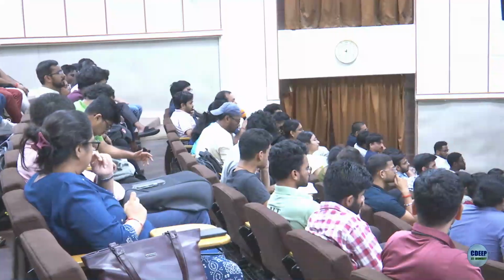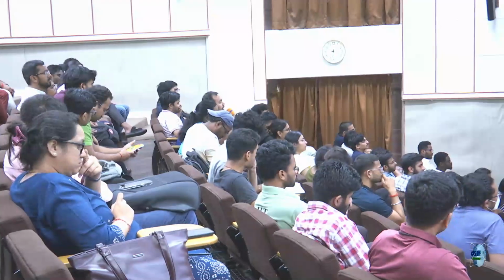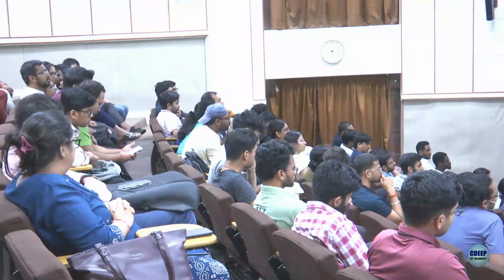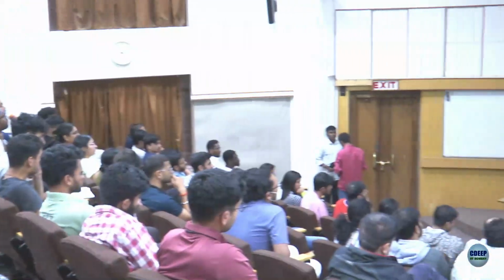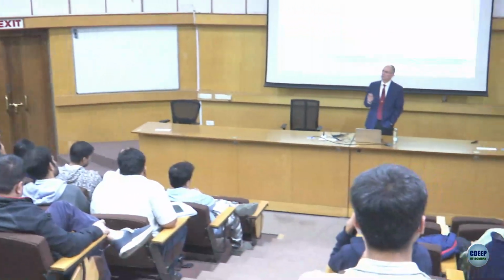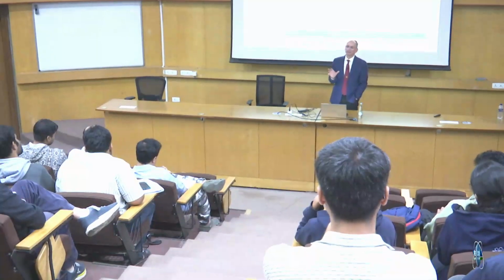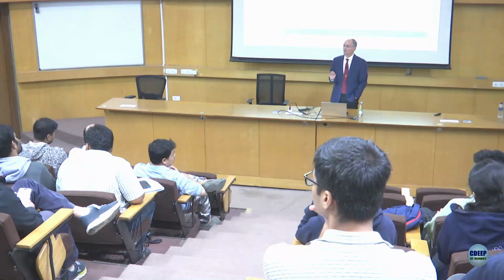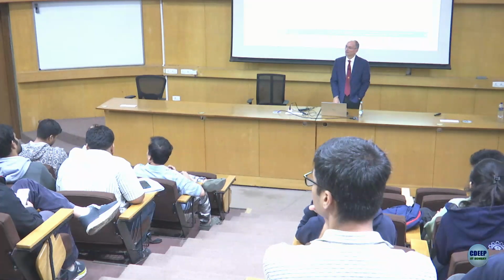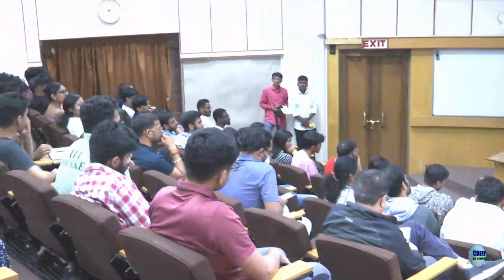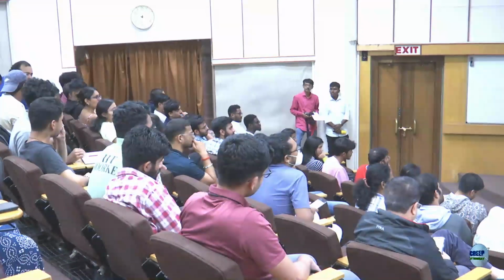Hello sir, this is Bhavya Bhargav, a PhD student working with Professor Rajiv Bandyopadhyay, Chemical Department. I wanted to know what are the sizes of the polymer molecules that you are using? About 30,000 grams per mole, above 5,000 grams per mole molecular weight. So the size of a molecule of this polymer would be typically near 1 micron? No, 30 kg per mole is like 7 nanometers, 10 nanometers, the radius of gyration.